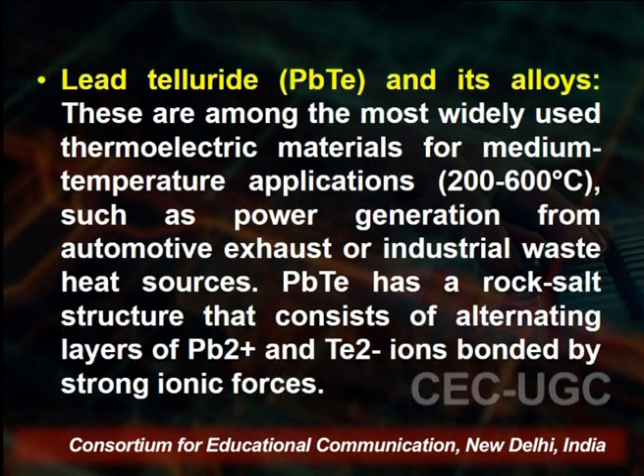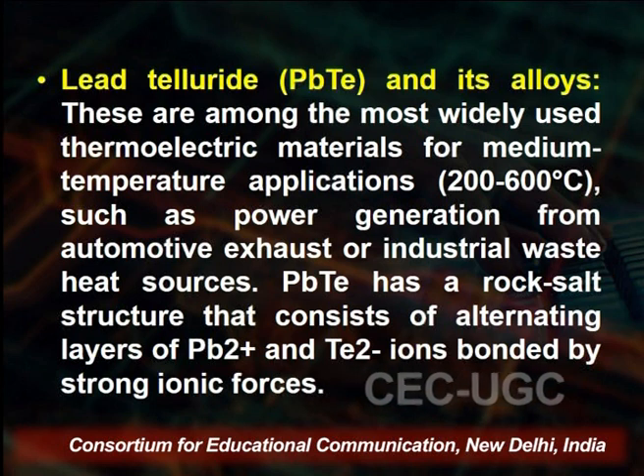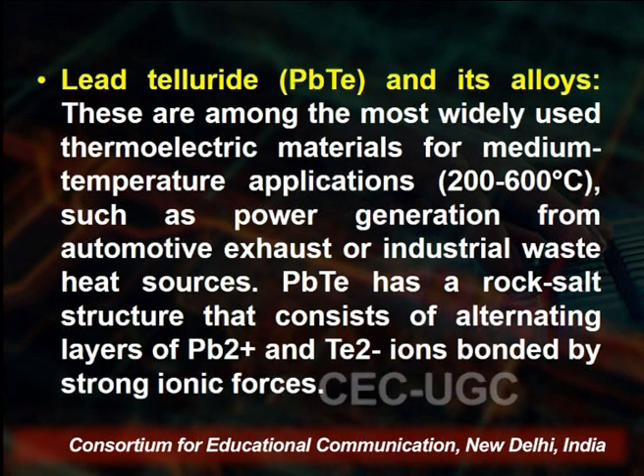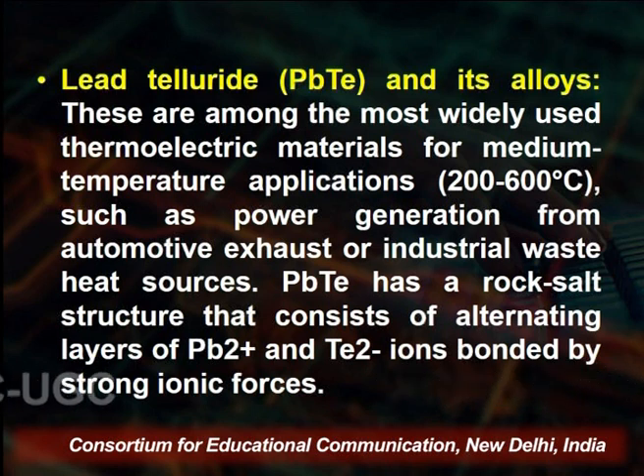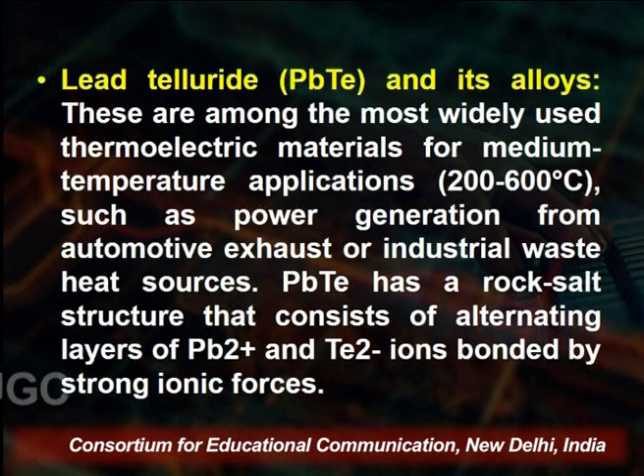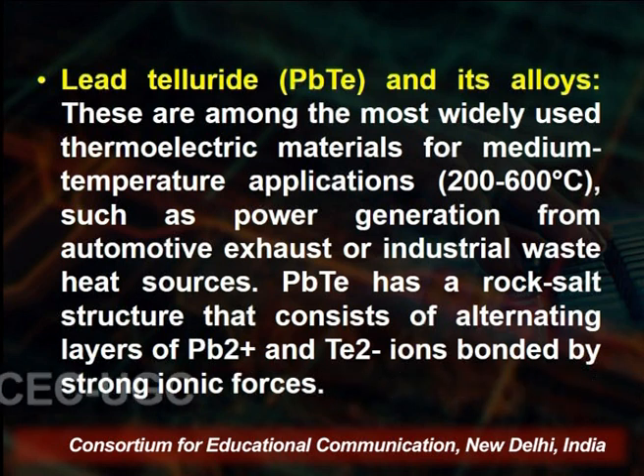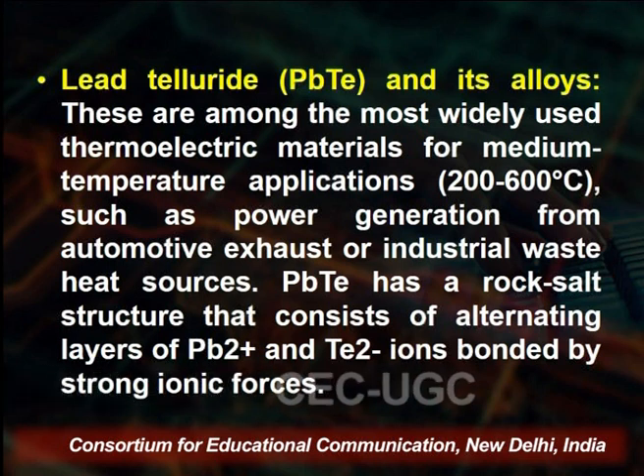Lead telluride, PbTe, and its alloys are among the most widely used thermoelectric materials for medium-temperature applications from 200 to 600 degrees centigrade, such as power generation from automotive exhaust or industrial waste heat sources. PbTe has a rock salt structure consisting of alternating layers of Pb²⁺ and Te²⁻ bonded by strong ionic forces.